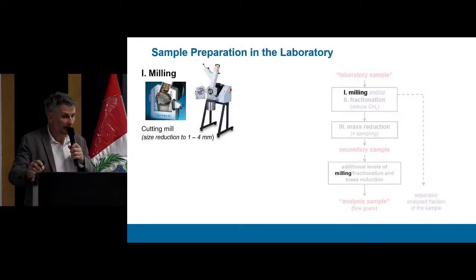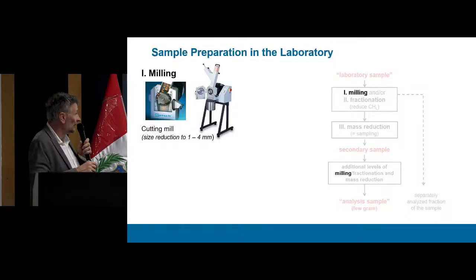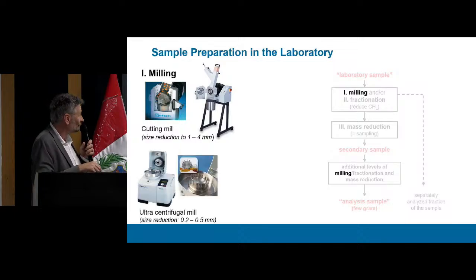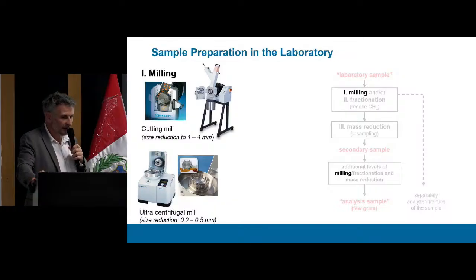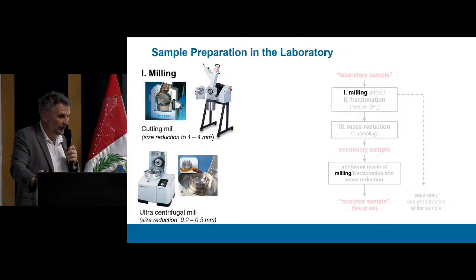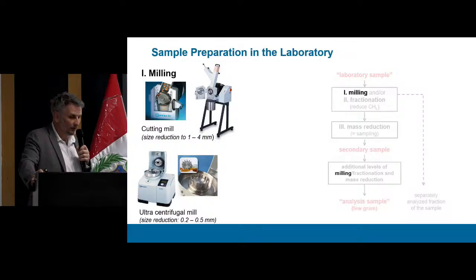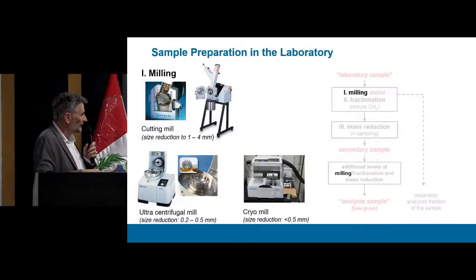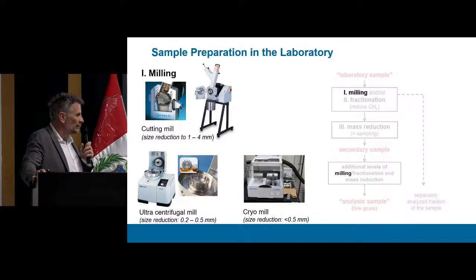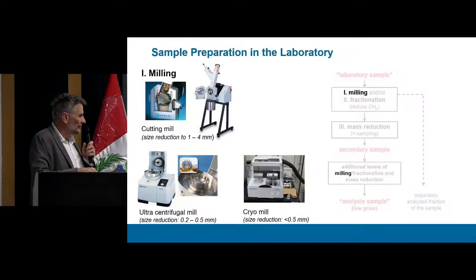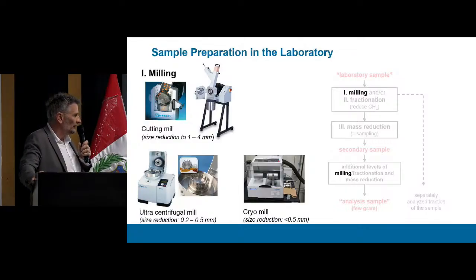These are typical devices we can use in the lab to reduce the grain size. This is a cutting mill, which allows us to have a size reduction to a size of about 1 to 4 millimeters. These are then further milling steps. Ultracentrifugal mill, which allows us to reduce the grain size to about 0.2 millimeter. And this is a cryo mill, which is cooled down, especially for milling plastics, which allows us to have a size reduction lower than 0.5 millimeter.